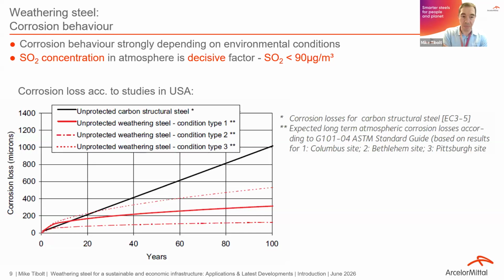And here we see an example of the corrosion losses according to a study in the USA. We see that over 100 years, depending on which environmental area we are, a more industrial area or a more rural area, the losses are up to 500 microns, compared to an unprotected carbon structural steel, which at this stage would have already lost 1 millimeter of material.